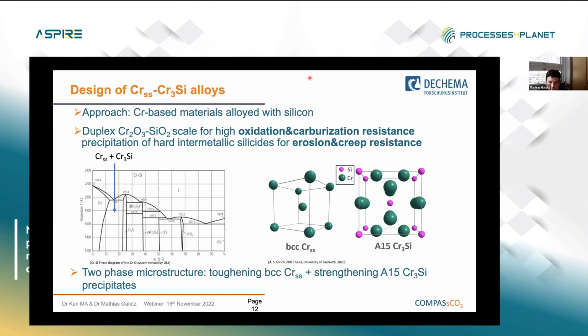conditions at high temperatures. Also, when we add silicon we get so-called A15 structured phases. As you can see here on the right side, you see the silicon and the chromium. It's an intermetallic phase, and these hard particles should be very good for the erosion properties that we expect in the particle CSP plant.